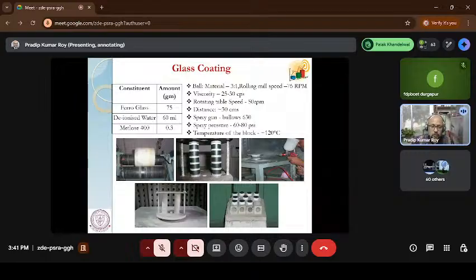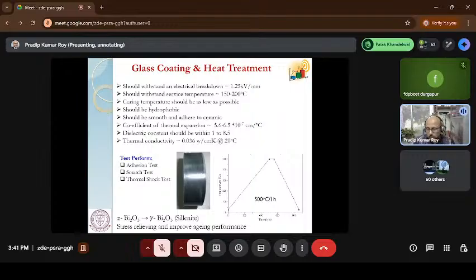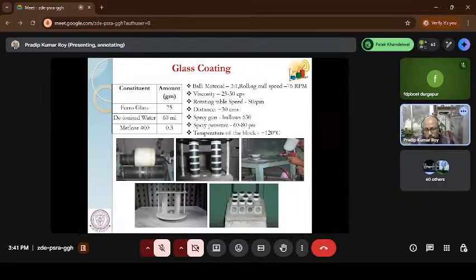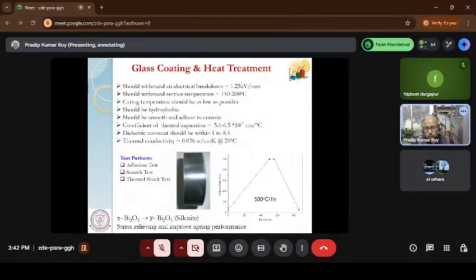After coating, they matured that at a certain temperature, around 500 to 600 degrees Celsius. You can look at the coating here: the glass is looking white, this is the green glass. Now after maturing it becomes completely transparent. We do some testing here, like adhesion testing, stress testing, thermal shock testing. These all tell how well this glass adheres to the ceramic body. That is very much required, because if any kind of gap is there between the body and the glass, there is a very high chance that flashover happens through that gap.